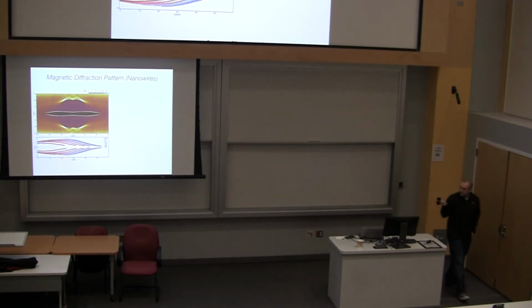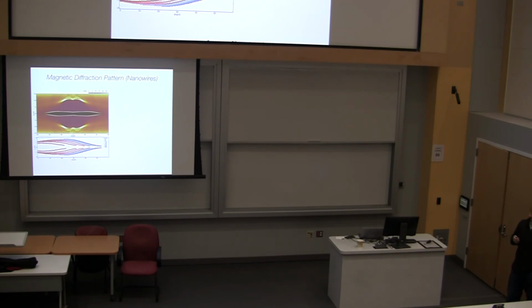Now, in our nanowires, what we see is that this Fraunhofer pattern is distorted, and there's actually a local minimum in the critical current around B equals 0. If you trace out this transition from black to purple, which is the transition from the superconducting region to the normal region, as a function of temperature, starting at 60 going up to 300 or 400, I can't remember, what happens first is there's not a uniform drop of the shape as temperature increases, but these peaks, these anomalous lobes that have a higher critical current at a non-zero magnetic field, are the first ones to die out. You see there's a much stronger dependence here than there is here. And then once you get into the high temperature regime, you start to recover a more normal Fraunhofer looking pattern.